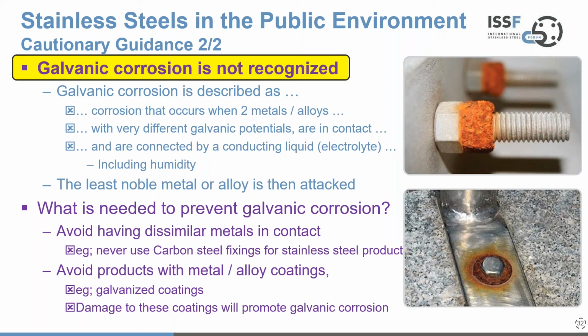And then avoid products with metal or alloy coatings, because when you tighten these things up, you're likely to damage those coatings. An example of that is galvanized coatings. Once you start applying pressure and force to a galvanic coating, you will start to damage it, and then you will promote galvanic corrosion, because you have 2 dissimilar metals which will create the galvanic corrosion principle. So these are just 2 illustrative guides to say, hey, these are things that need to be thought about. And there are many examples of where these things have not been thought about.